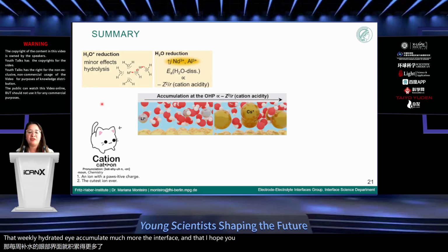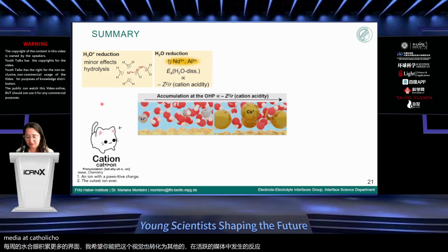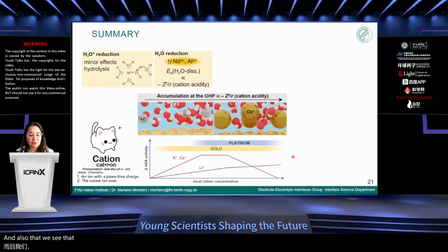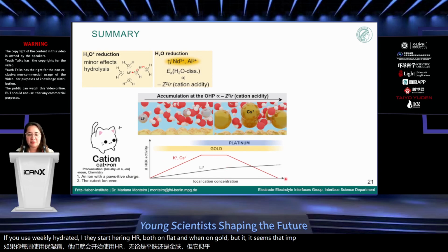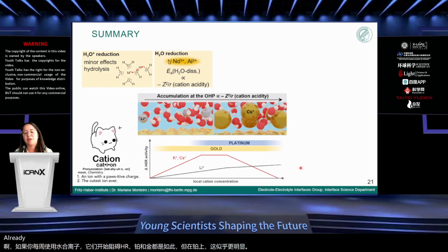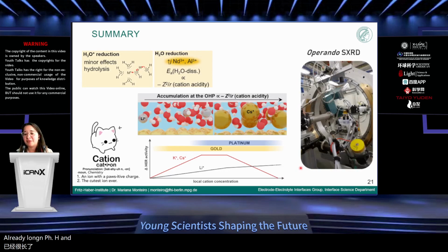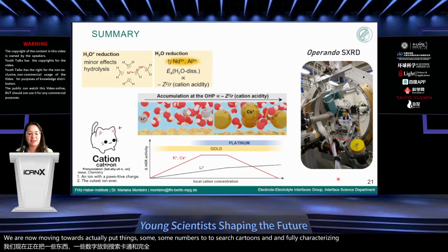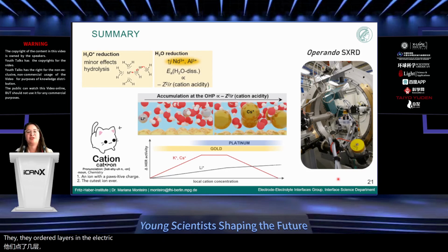And that I hope you can translate these insights also for other reactions happening in aqueous media at cathodic potentials. And also that we see that in strongly alkaline media or very high cation concentrations, if you use weakly hydrated ions, they start hindering HER both on platinum and on gold. But it seems that on platinum, this is much more pronounced already at low pH. And finally, that with operando surface X-ray diffraction, we are now moving towards actually putting some numbers to our cartoons and fully characterizing the ordered layers in the electrochemical interface.